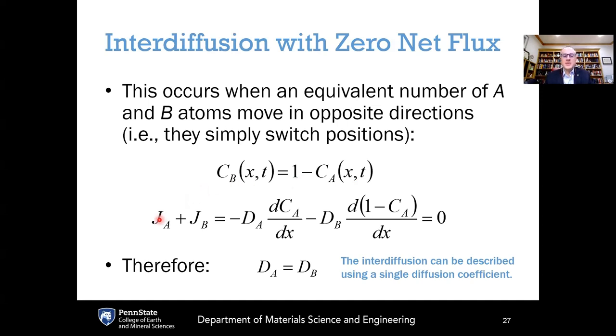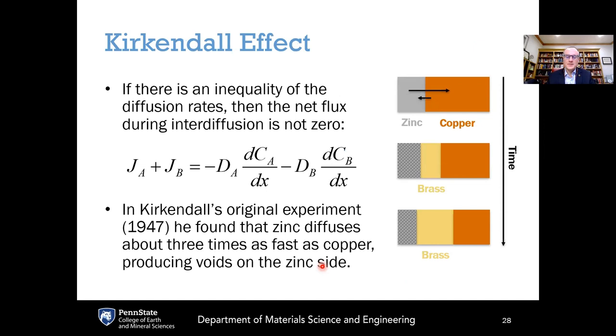So in other words, if you take the summation of the flux of A plus the flux of B, we're summing up our flux equations, and the second one here for B, this concentration for B can be written as 1 minus the concentration for A. And summing that up, if that equals zero, how do you make this equation equal to zero? The only way you can make that equal to zero is if DA equals DB, or in other words, the diffusion coefficient of A is equal to the diffusion coefficient of B. And what that means is that the interdiffusion process, even though it involves two different species, can be described using a single diffusion coefficient D. So that is what happens if the net flux is zero.